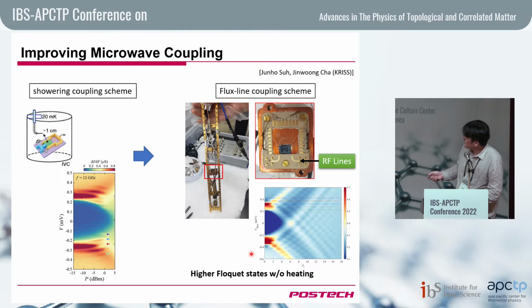What we are doing these days is improving the coupling scheme between the antenna and the graphene. Previously it was a very lousy way to couple the microwave. We just put the center pin near the sample by hand. But now we are fabricating an on-chip RF antenna so that the distance between the antenna and the sample is much closer. So now we can see many replications of the state without heating the sample too much. If you see, for example, 20 copies of the state, that means you have roughly beta equals 20, which is much larger than 1. Previously, it was of order 1, but now we can have beta of order 20 without heating the sample. And probably that can lead us to more interesting Floquet physics in a stronger interaction regime.